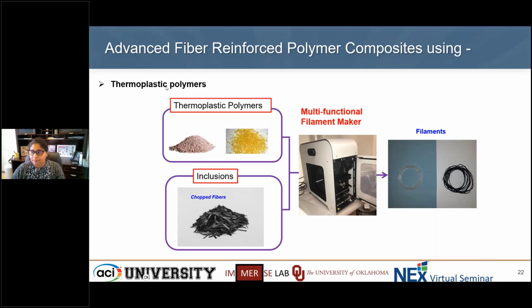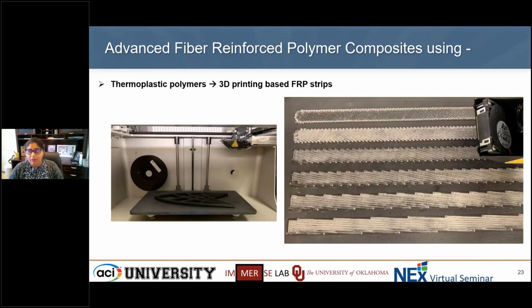What we used is a market-approved, Markforged tabletop kind of 3D printer, which has the capability of a dual nozzle, which more importantly means that it is able to print both thermoplastic and a fibrous material on the same layer of the specimen or the composite. So if you see here, this is a spool that contains the fiberglass, which looks like this, the transparent fiberglass coming out of that nozzle, and it can basically be printed on this print bed here.